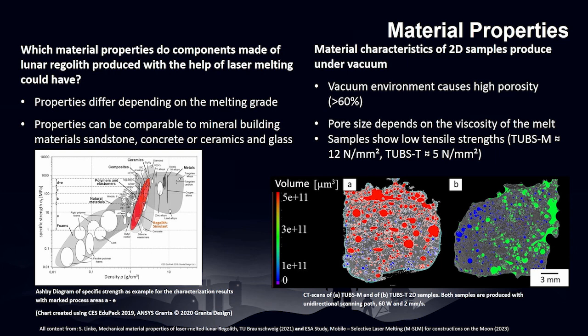What we also see is when we work in vacuum, we have materials with a high porosity, up to 60%. Depending on the viscosity of the melt, which depends on the type of regolith simulant or the regolith itself, we have a high amount of small pores, or if the viscosity is lower, a few pores of a higher diameter. Also, we make some mechanical tests, for example, tensile strength tests, and with these, we found that we have in the samples tensile strengths up to 12 newton per square millimeter, which is typical for these materials.